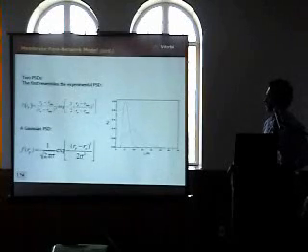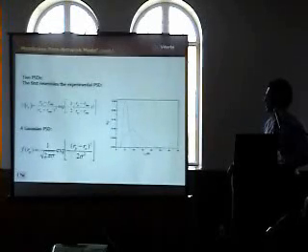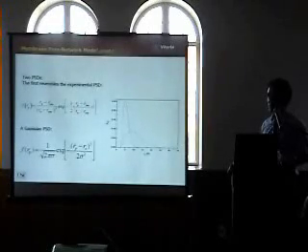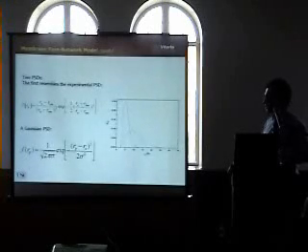We used two different pore size distribution models. The first is similar to most experimental membrane pore size distributions, and the second is Gaussian. We used different average pore sizes to study the effect of the average pore radius R_A, and assigned R_minimum to be equal to the molecular size of helium. For the Gaussian distribution, we changed the variance to study the broadness of the pore network.